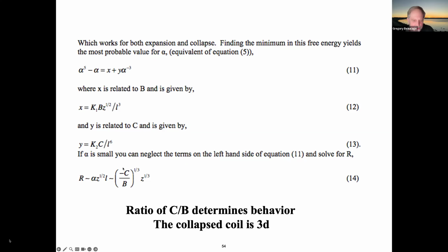So this is describing the globule size in terms of the third virial coefficient, the second virial coefficient, and the cube root of the molecular weight because it's a 3D object. So r cubed goes with z, which means it's 3D. The power of r is a dimension, so that checks out. And then you have this metric for the third virial and second virial ratio. So that kind of determines the behavior of this thing.